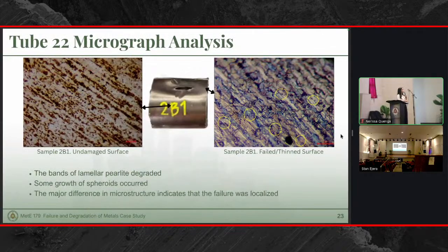We conducted micrographical analysis to further confirm our suspicions, and as we can see, the failed or thinned surface had degraded bands of lamellar pearlite and some growth of spheroids, and the major difference in microstructure indicates that the failure was localized. So this is the micrographical analysis for the area with the rupture.